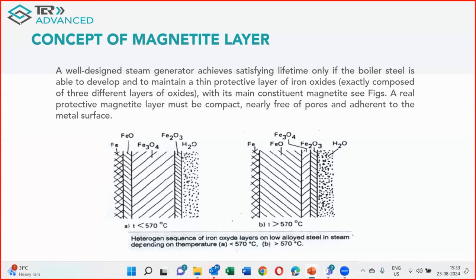It is said that when tubes are operating more than 10 degrees above the design temperature, that is skin temperature, the creep life reduces to 1/10. Now this increase in temperature further increases the scale thickness. It also increases the skin temperature, and the tube life is drastically reduced. So long-term overheating will occur and a creep failure will occur. So operation has a lot of bearing on the damages and the life of the boiler which we observe.